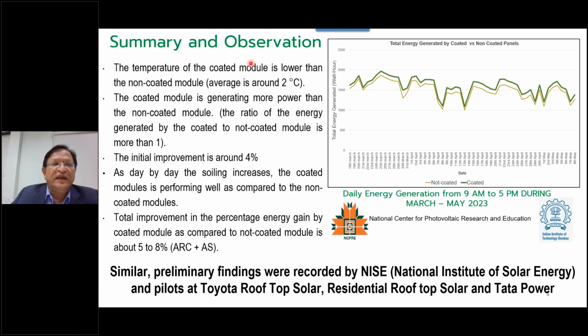NCPRE have summarized that the temperature of the coated module is lower than the non-coated. So the cell temperature, because of the coating, goes down by about 2 degrees. And then they said that from day one, the coated panels had a higher energy output, energy generation, by 4%. And that is because of the anti-reflective property of the coating. But as the panels are exposed to atmospheric conditions, the soiling increases, and therefore the energy output delta between coated and uncoated goes to 5 to 8%. So first is the anti-reflective coating, by which you are getting 4%, and then as the soiling or dirt on the panel increases, or the exposure to atmospheric conditions happens, the energy efficiency goes further up to 8%.